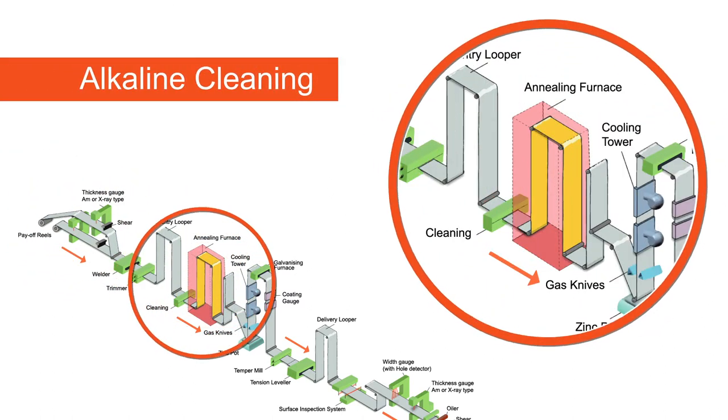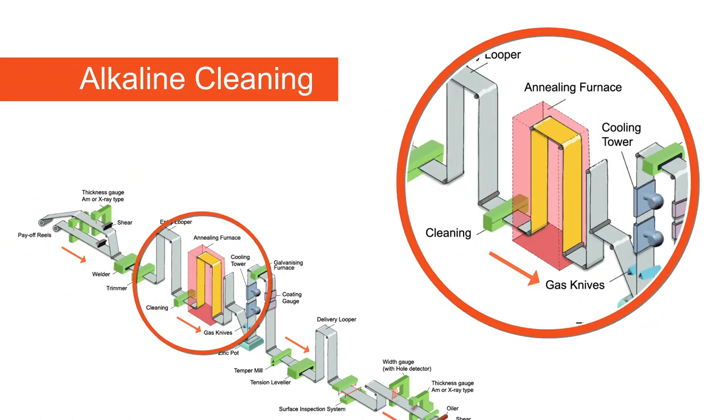An alkaline cleaning section to remove the rolling oils, dirt, iron fines, and surface contaminants from the cold reduction process that are on the sheet surface.